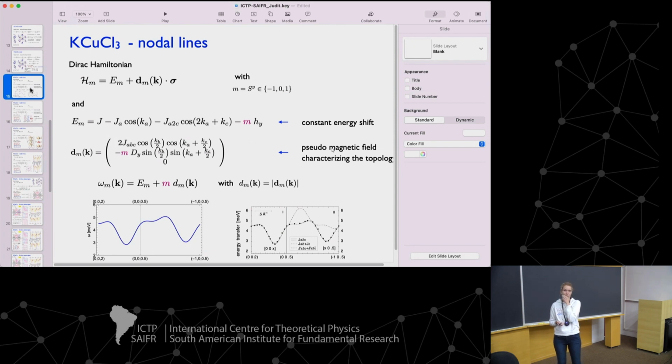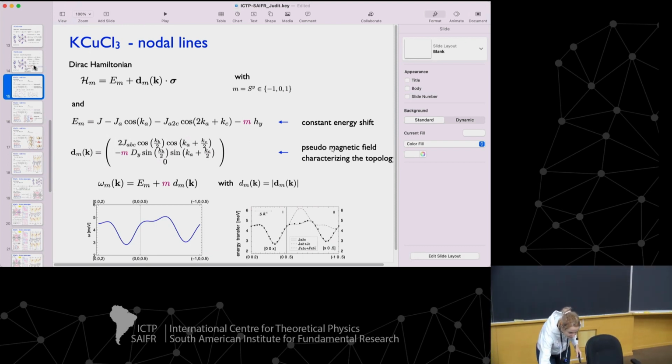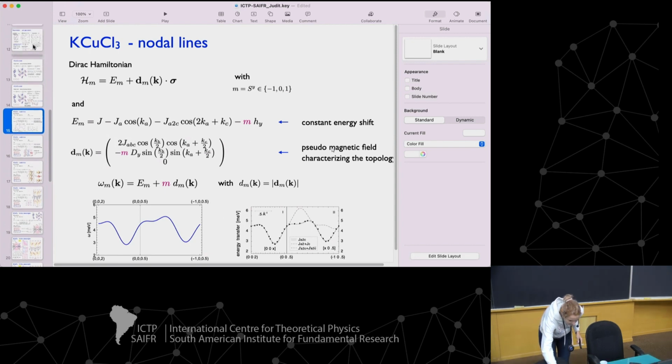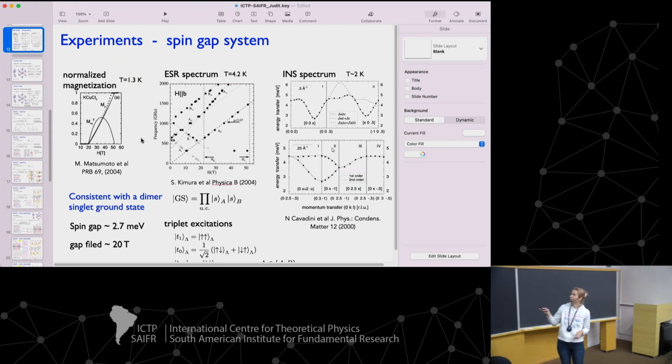This was actually the case for strontium copper borate. The first neutron spectrum didn't show the splitting from the DM interaction because it was too old and the resolution wasn't good enough. And I don't know how big the DM is. The ESR spectrum, if you look at it, at least from this earlier measurement, is very misleading. It's not this gap, the DM. It looks like it is, but it actually isn't. But this A mode here at the bottom has a double peak structure, and they say that this is actually coming from the Dzyaloshinskii-Moriya interaction.